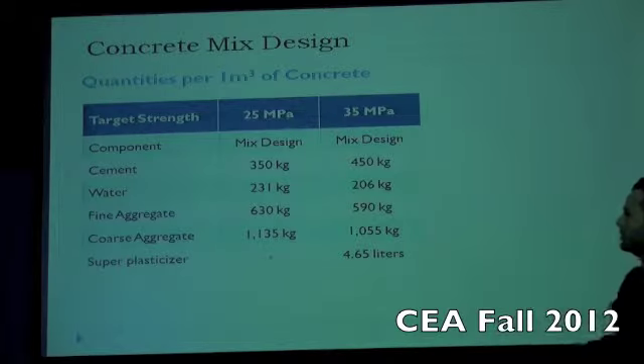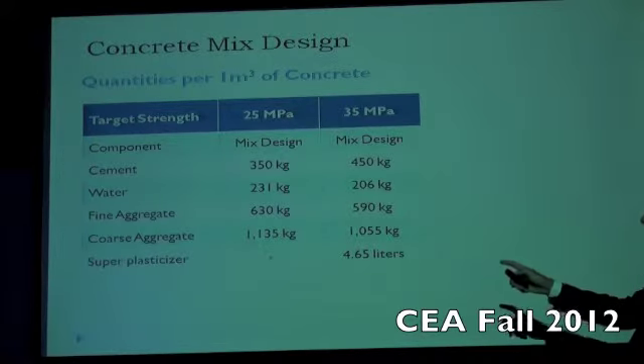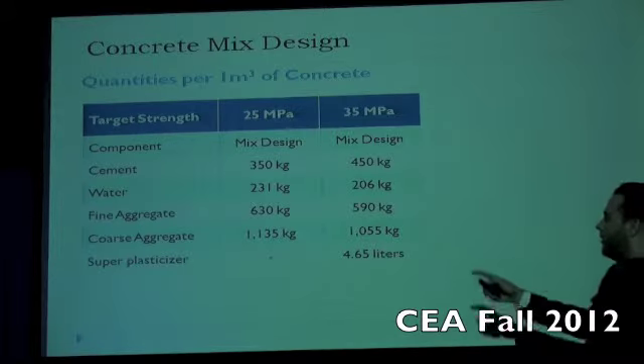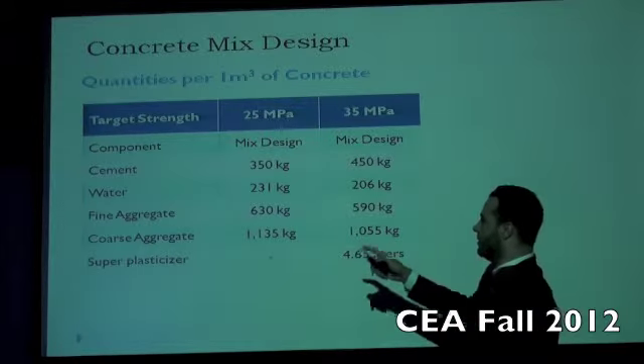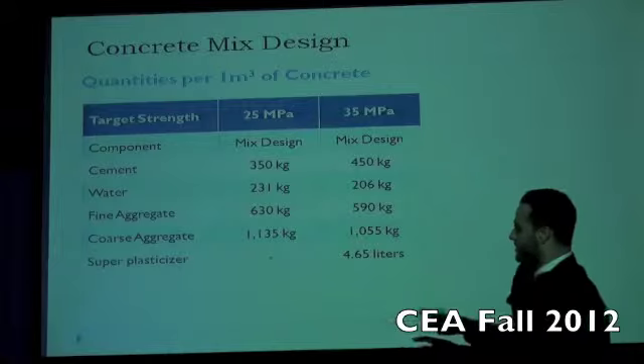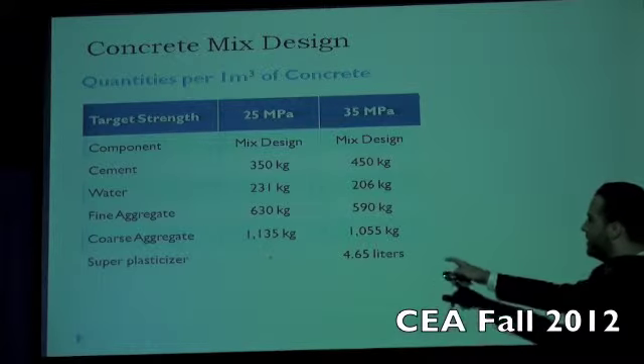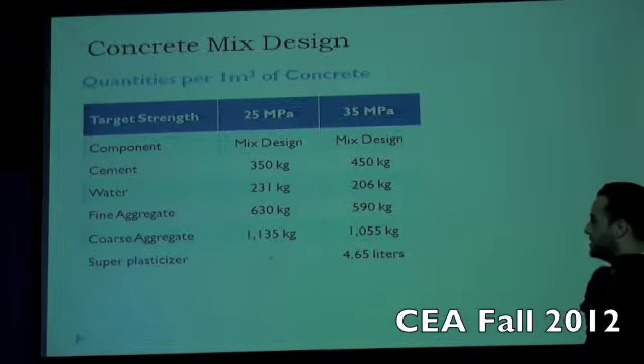Here is the mix design we use for the 25 megapascal and 35, and the amount of every component: cement, water, fine aggregate, coarse aggregate, and superplasticizer. We only use it in the 35 megapascals.